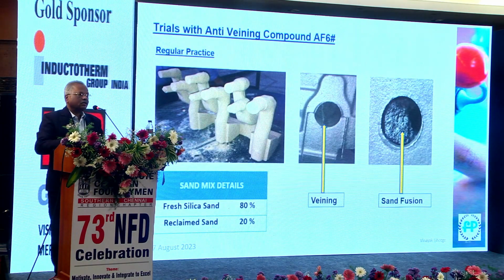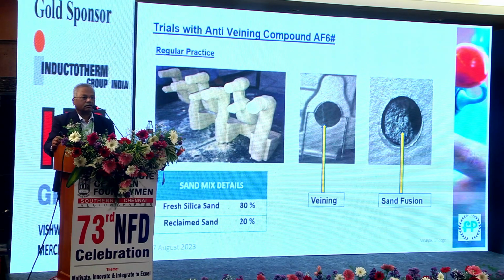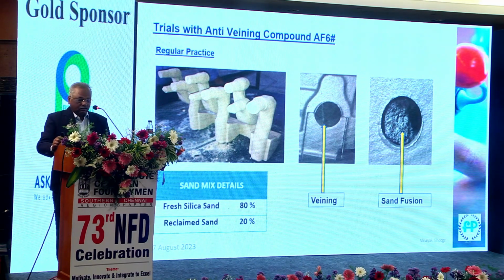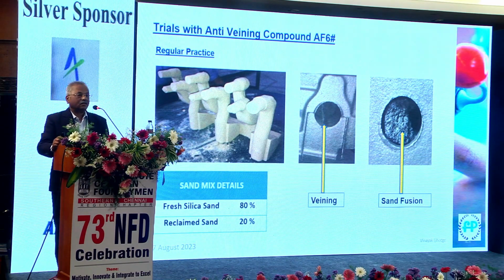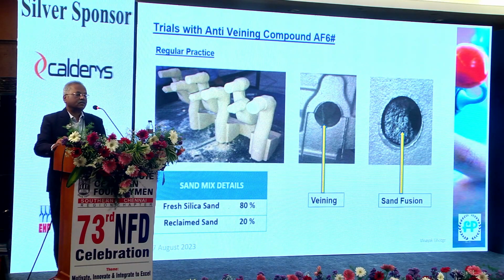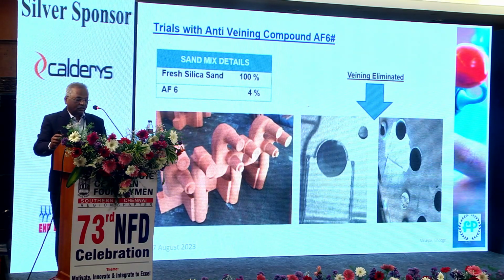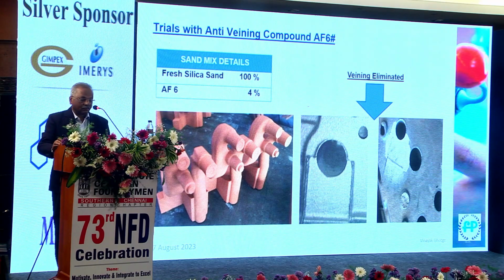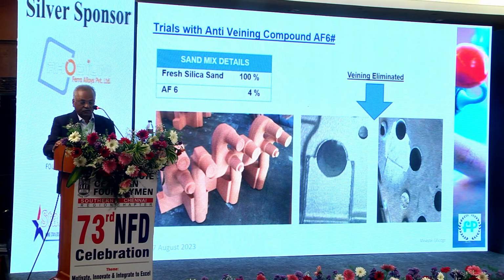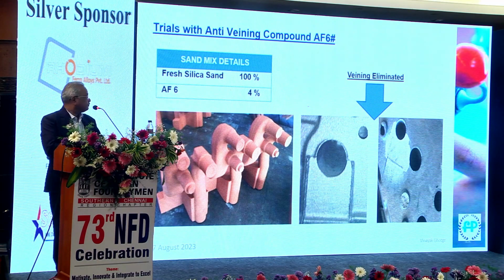I'll just go through quickly the certain field trials we had taken in some foundries. This was a foundry where they were earlier facing a problem of veining as well as sand fusion in the cylinder area. They were using fresh silica 80% and 20% reclaimed sand, and this trial was taken with only 100% silica sand with anti-veining compound about 4%, and if you see, the veining was eliminated, and even the sand fusion, there was no sand fusion.